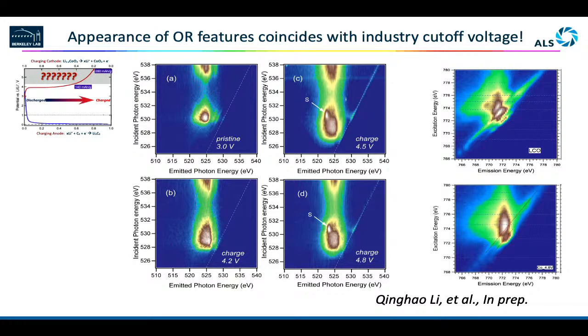So when we do a RIXS map on those, what we see is a happy but also a sad coincidence. When we look at this kind of feature in the lithium cobalt oxide, we measure all the way up, step by step, to 4.2 volts. Nothing happens. Right above 4.2 volts, at 4.5 volts, boom, you see this feature start to show up. And then if you look at the cobalt, however, the cobalt starts to change from the very beginning. It doesn't give you this kind of step behavior.